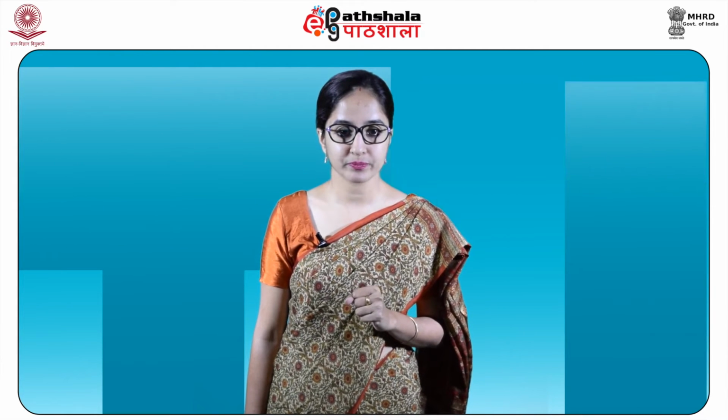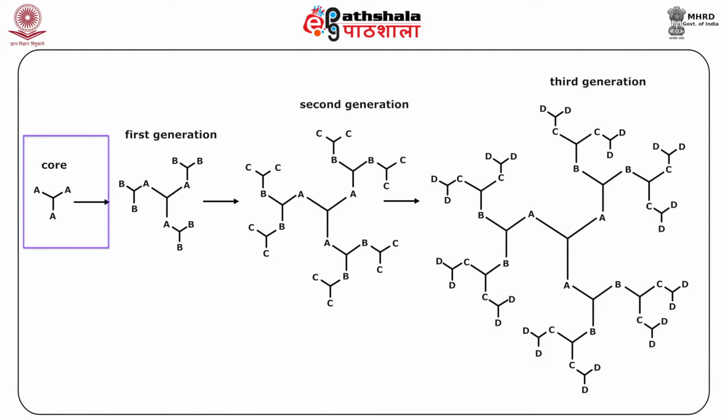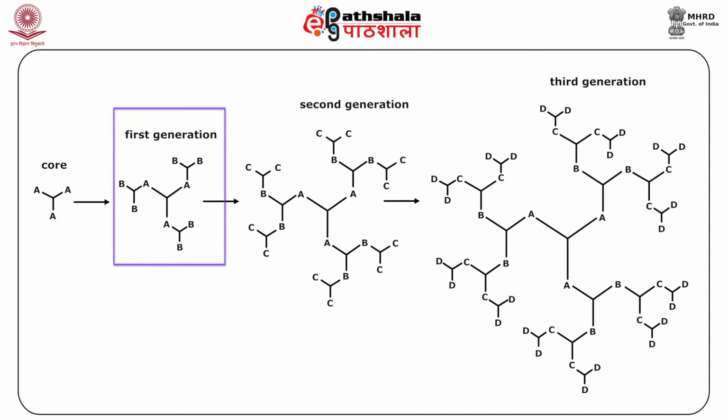Structurally, a dendrimer begins with a multifunctional core. Numerous molecules like ammonia, pentaerythritol, benzene, adamantane, porphyrin or even fullerene can be used as dendrimer cores. From this core, an oligomer is generated by the attachment of a multifunctional repeating unit with a core functional group. This oligomer contains a central core and a number of functionalized pendant arms. This is the first generation dendrimer. That is the first step to generating a dendrimer based structure.